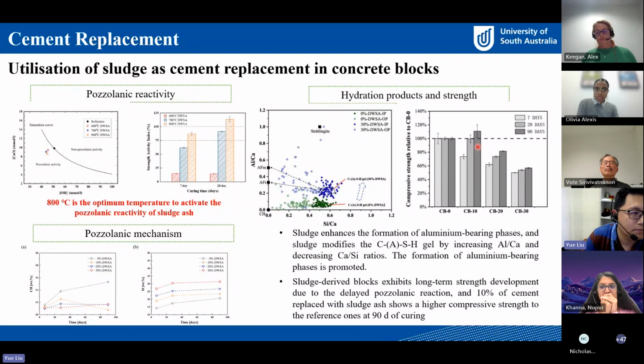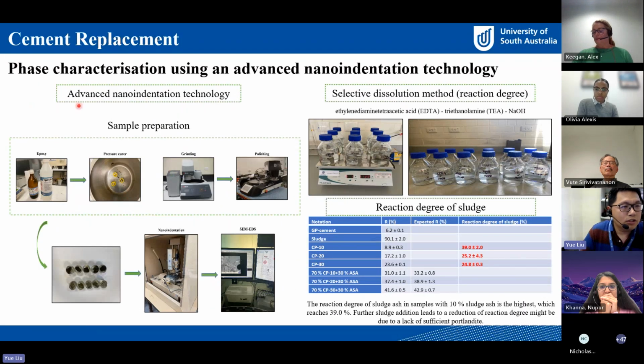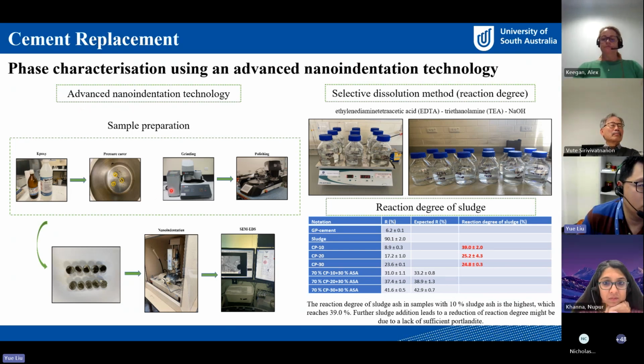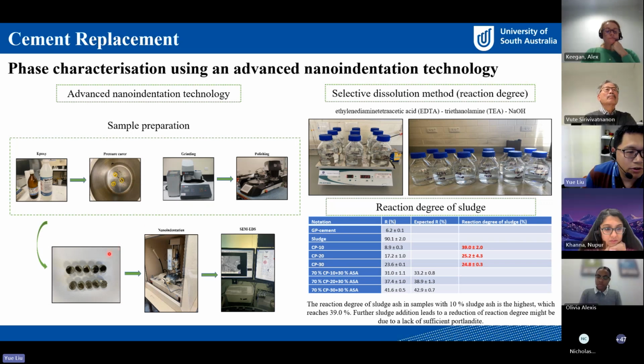calcium hydroxide. To further analyze the reaction mechanism of sludge in cement-based composites, we did advanced nano-indentation and also the selective dissolution method. This is the sample preparation procedure for the nano-indentation test. We put fractured pieces into epoxy and then grind and polish the epoxy to achieve a flat enough